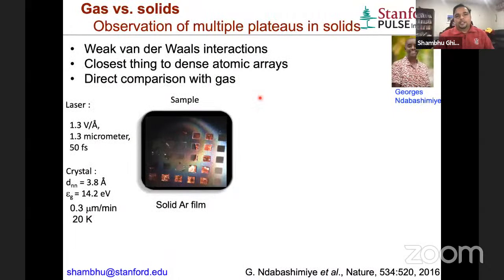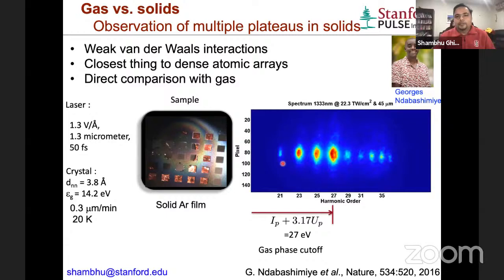So this is another example in terms of trying to understand the similarities and differences between the atomic and the solid state high harmonic generation process. This is nice work done by Georges Ndabashimiye from our group. He did the experiment. This is the sample of solid argon. This is the measured spectrum, and you can see there are actually two plateau-like features that we observed in solids for the first time. So the first plateau extends to almost the atomic limit, and there is this secondary plateau that is not there in the gas phase.